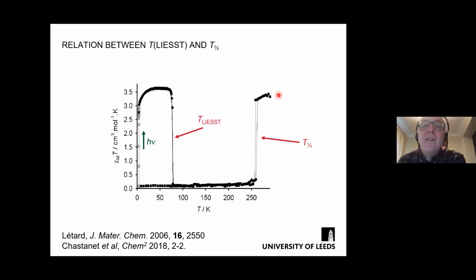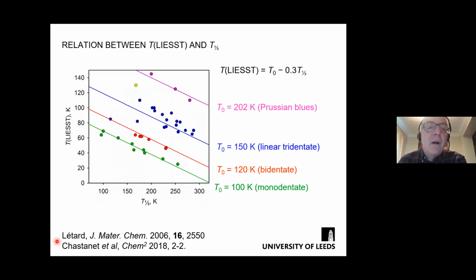So, I mean, this is nice. You can think of this, that we can study the same process of the same spin state conversion under thermodynamic and under kinetic conditions by doing this experiment and look at their relationship. And if you plot a graph of the thermodynamic versus the kinetic spin transition temperatures, this was noticed by the Bordeaux group quite a long time ago now. What you see is you get quite a linear relationship as long as you only compare the same kinds of molecules. So these are molecules with monodentate ligands. These are molecules with bidentate ligands. These are molecules with tridentate ligands like ours. There's a lot of scatter here, but you can still just about see a graph if you look hard enough.